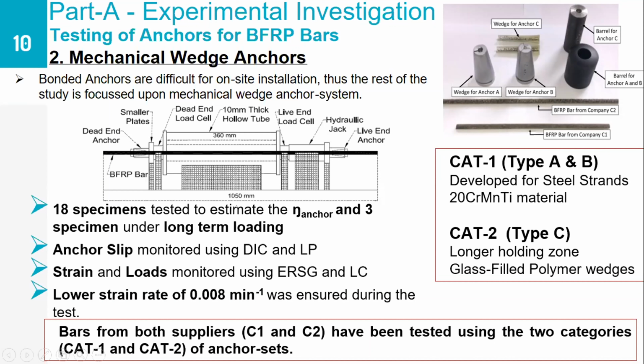So 18 different specimens have been tested to estimate the anchor efficiency, and 3 specimens have been tested to study the relaxation loss or the long-term loading effect. And the anchor slips in these tests have been monitored using the digital image correlation technique as well as using linear potentiometers. The strains and loads have been monitored using strain gauges and load cells respectively. And a smaller loading rate than what is recommended by the standards, 0.008 strain per minute, has been applied during the tests.